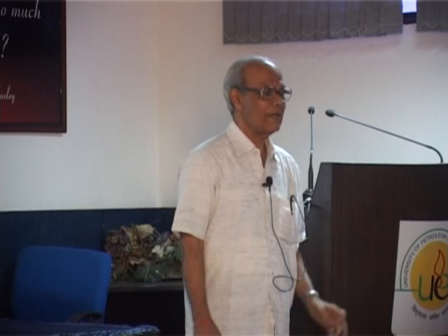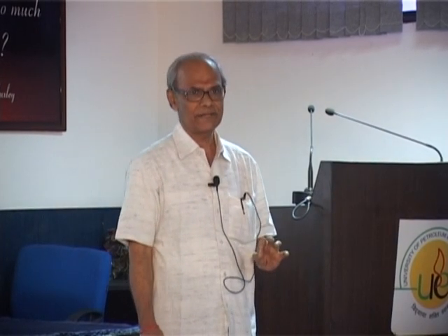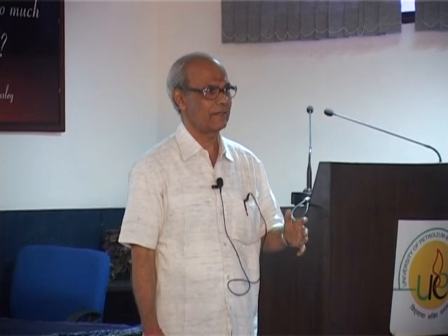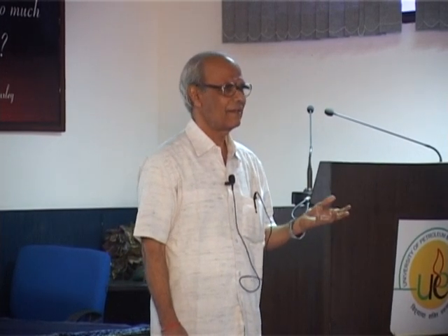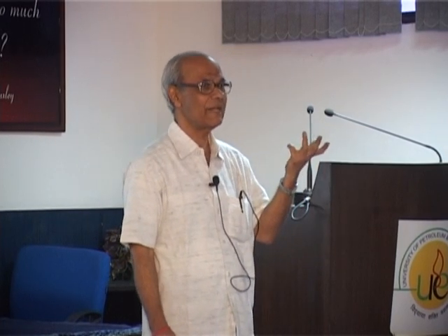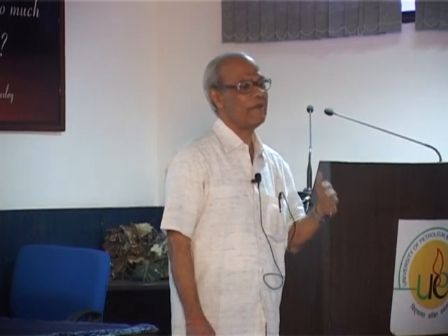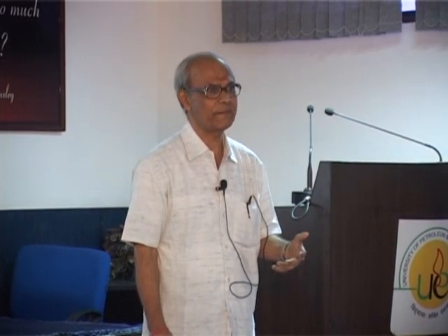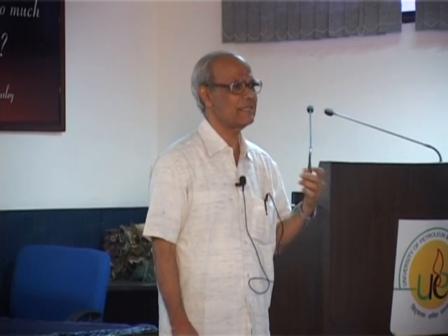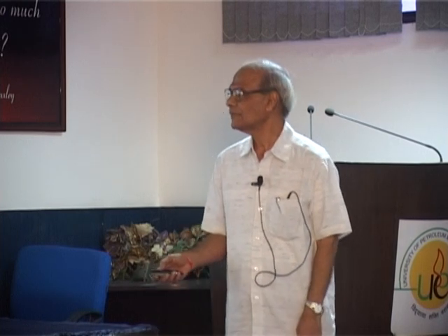So, what am I doing? Like in the case of gold particles, I have used a chemical reaction to produce the product at a very rapid rate. So, what happened in the gold particle case? Supersaturation got built up very, very rapidly. Therefore, nucleation rate increased. So when I am trying to draw current very, very rapidly, I am nucleating particles very, very rapidly. That is the first effect.